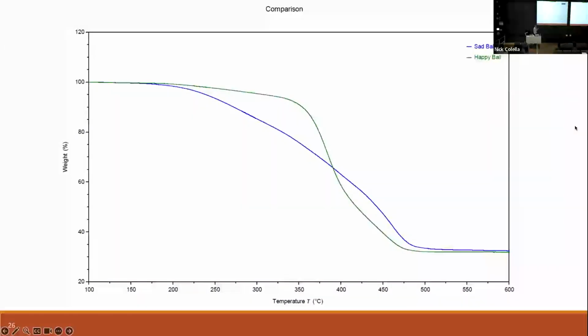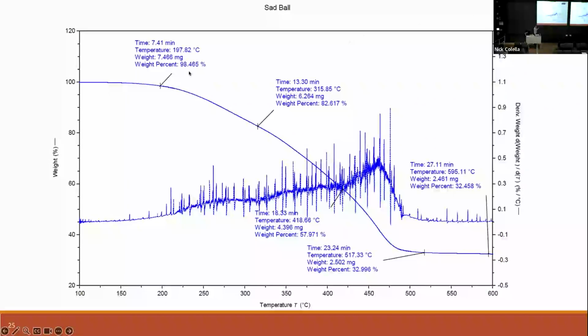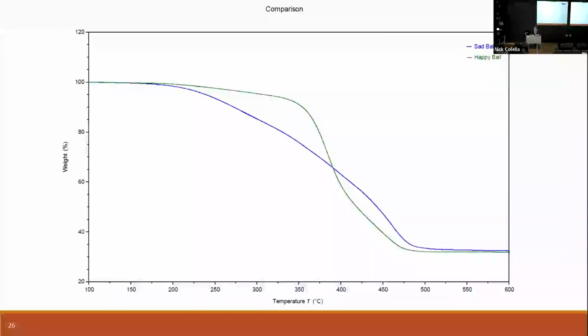So comparing the curves for the happy ball and the sad ball, I missed my sad ball curve. So the sad ball starts to degrade much more quickly, starts at 200 degrees or so, and then we get a slow decomposition profile. So that gives us another hint that these are different materials that we're working with. So comparing the curves, we can see the onset is kind of similar. We see a slow degradation here, but the sad ball degrades much more quickly at lower temperatures. And then they both kind of end up at the same spot.